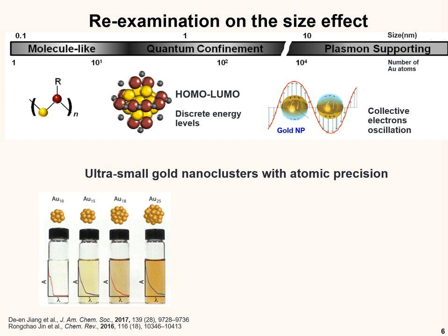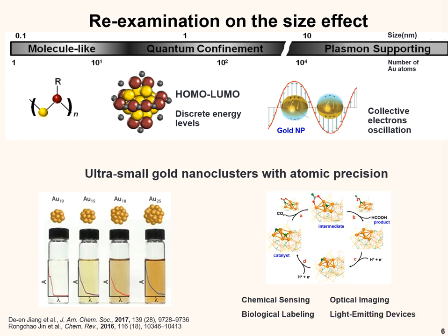Here I'm not going to go into detail, but we found that the optical properties in this cluster are significantly different from what we saw in the gold nanoparticle. The application is also quite different because the quantum confinement is dominant. So like a molecular system, you can pump your electrons into excited states. These excited electrons will be very useful in some photocatalysis results. So two different nanoparticles have two completely different relaxation dynamics and also completely different applications.